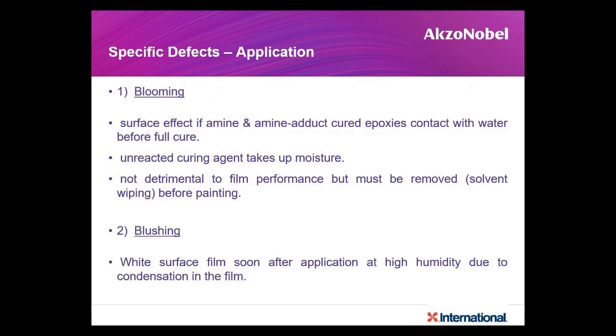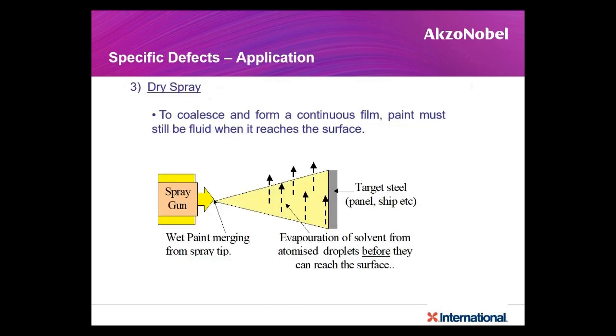Blooming: amine bloom is the reaction of a component of the paint, which is part B, an amine adduct, to the air and moisture before full cure, which will form a milky kind of finish on the substrate, which will not react, but it will also be very streaky sometimes. So it is not detrimental. It will close at any point in time. Of course, blushing is also there, which forms a white surface. Then you have the dry spray application issue, where the paint flows into the other areas, thereby causing issues in terms of drying of paint droplets in other areas. So I have shared a few defects only.